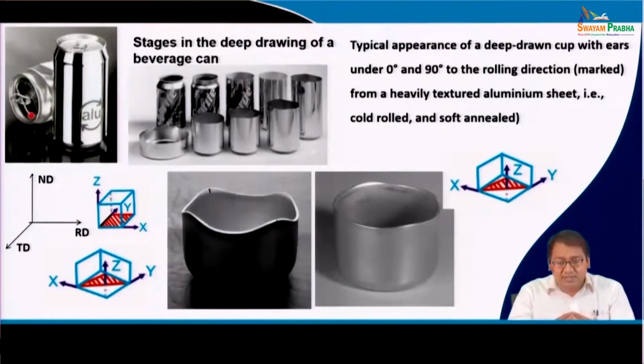Now, initially aluminum cans or other cans were produced by simple operations of deep drawing, of course, but the understanding of R bar affecting deep drawing ability was not that much. And so, a large deep drawing of cups was not possible, and there was always the formation of ears and faces, because delta R was also not maintained. Therefore, there was usually a large loss in revenue for the companies making these deep drawn cups, because they had to chop off the faces and the ears and make it straight before supplying.